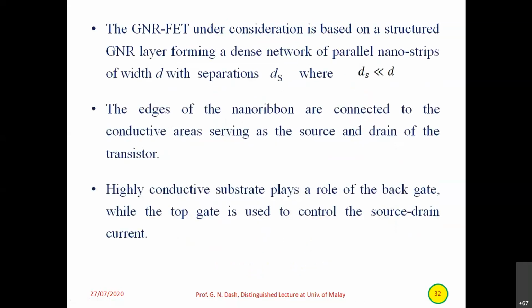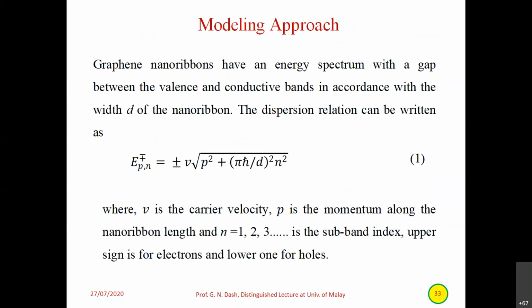The GNRFET under consideration is based on a structured GNR. Instead of a single GNR, which can support only a small amount of current, we can take an array of graphene nanoribbons, and the distance between them is very, very small. Es is the distance between two, which is much less than D. D is the width of the graphene nanoribbon. So I have changed the symbol. The edges of the nanoribbon are connected to the conductive areas serving as the source and drain. A highly conductive substrate plays the role of the back gate, while the top gate is used to control the source-drain current.